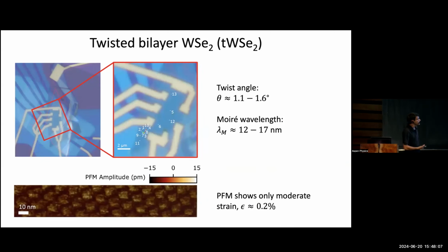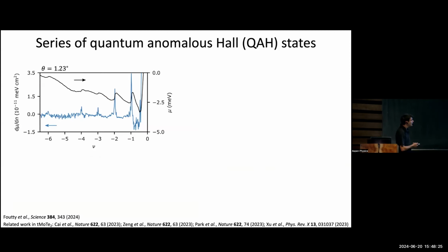We wanted to look at this in twisted tungsten diselenide homobilayers. So again, this is the sample that we have. Twist angle ranges from about 1.1 to 1.6 degrees. That corresponds to a Moiré wavelength of about 12 to 17 nanometers. So we have about a factor 1.5 change in Moiré wavelength that we can explore in this system.